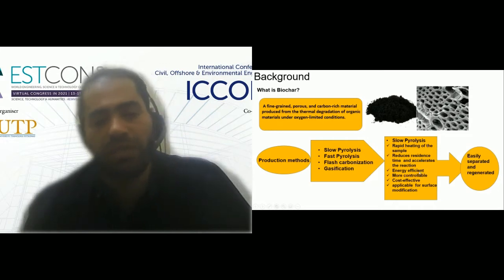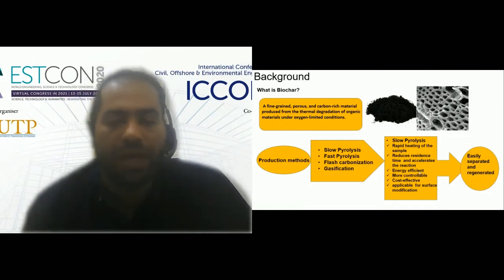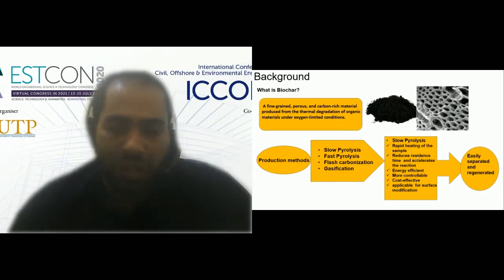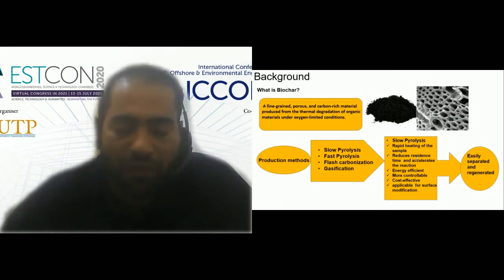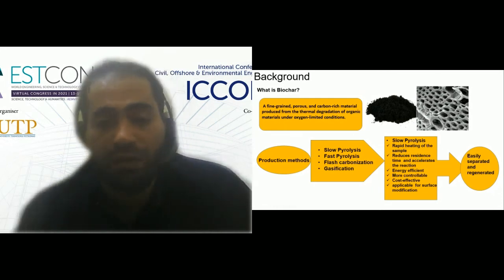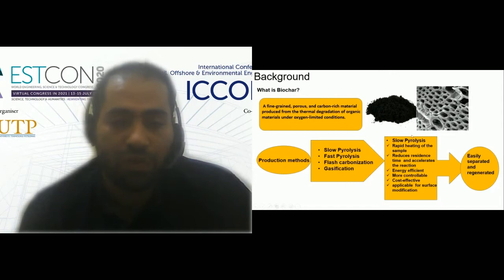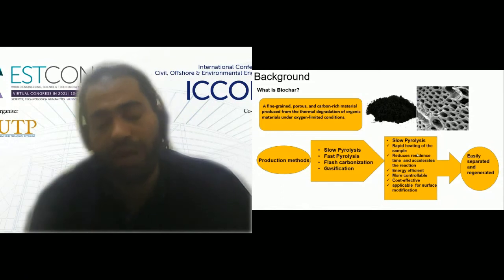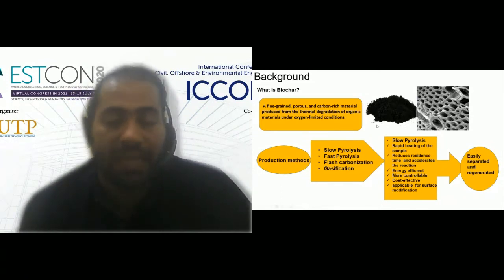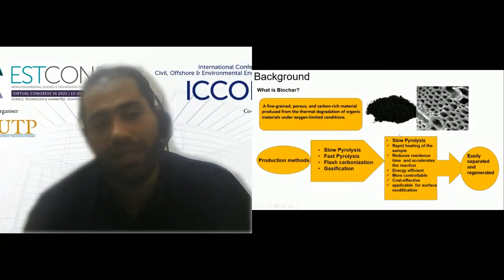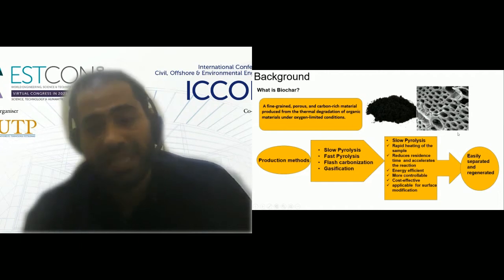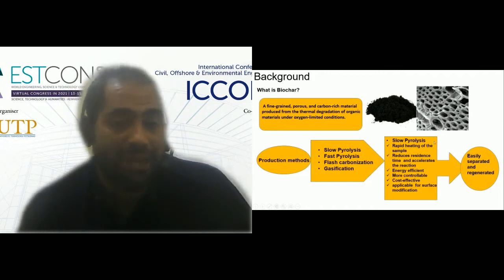When the pyrolysis is slow, we can control the heating time easily, and it is also cost effective compared to other commercial absorbents, and applicable for surface modification. When we have biochar produced using slow pyrolysis, we can modify it as we want, like what we have now. We impregnate the biochar with iron oxide in order to get the added value of being easily separated and regenerated again and again.